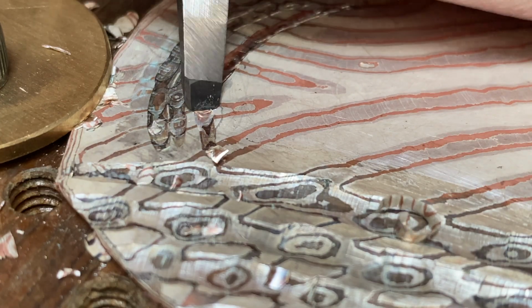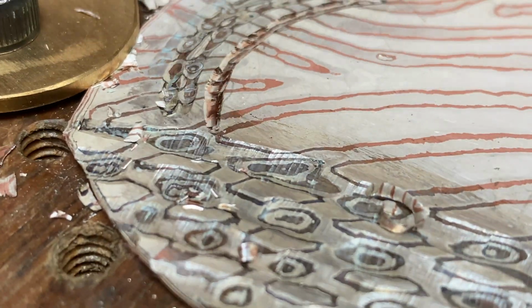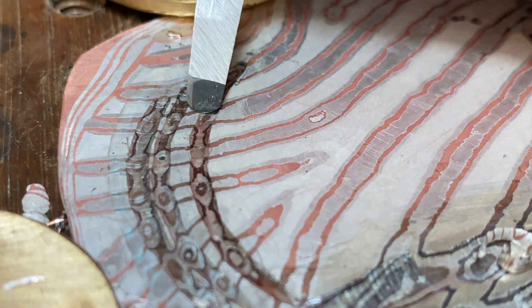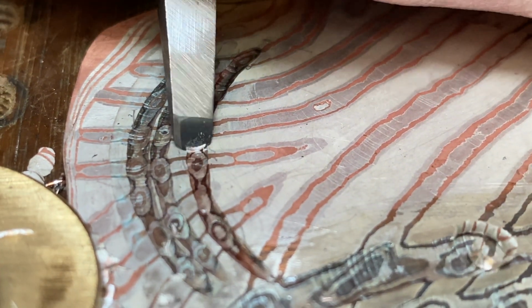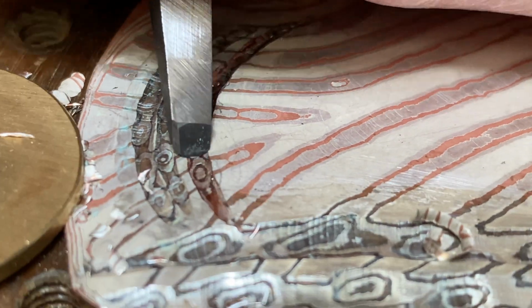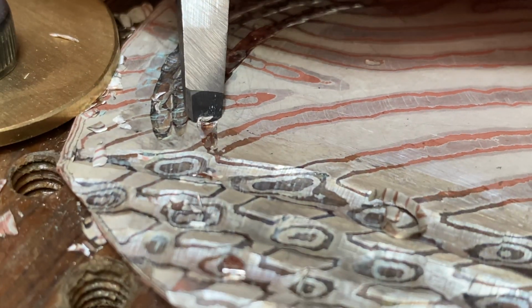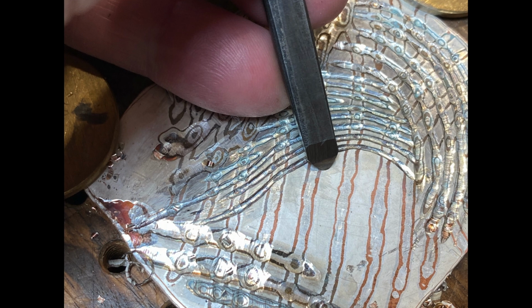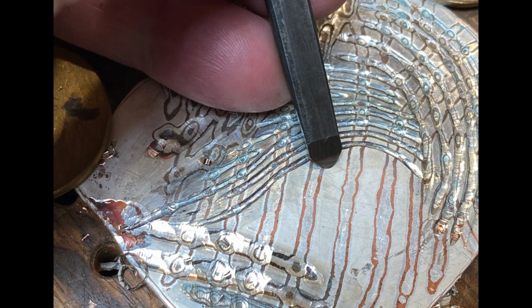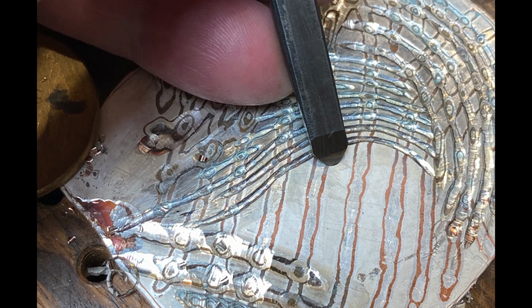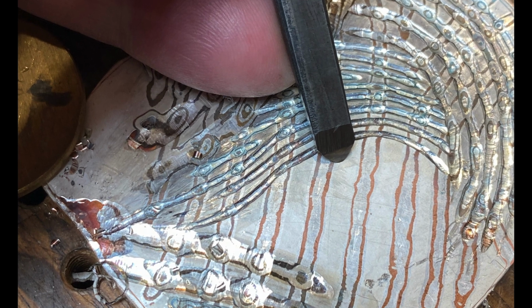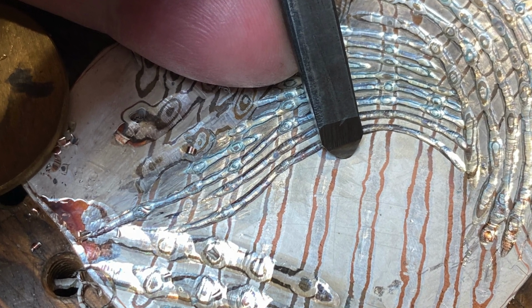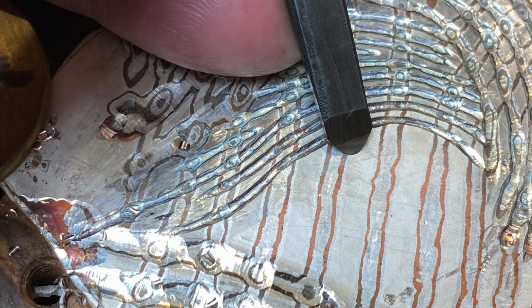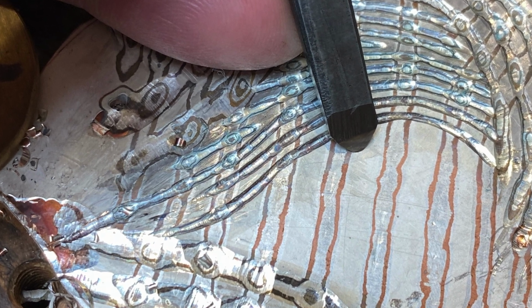This type of patterning, stopping at a certain depth, isn't easy. That's the bad news. It does give a result that I think is worth the trouble. But the good news is this type of patterning works at any depth. What happens if you cut the crossing channels without forging anything flat? Quick, fast. I tried it, and the little pyramids between the crossing cuts just popped off. It was a total mess. But there might be something there, so give it a try if you want.